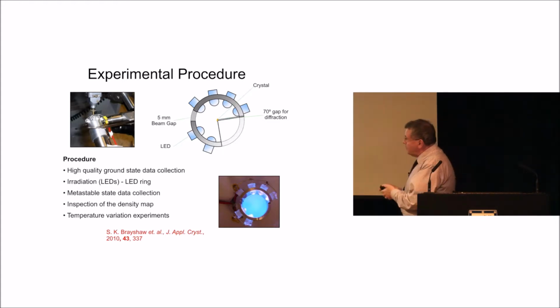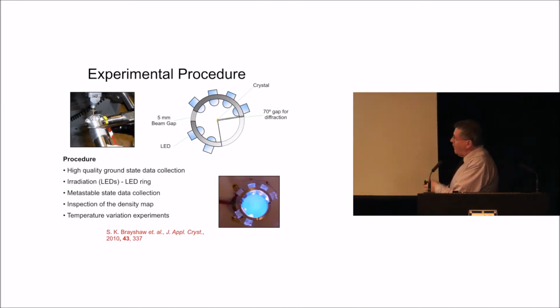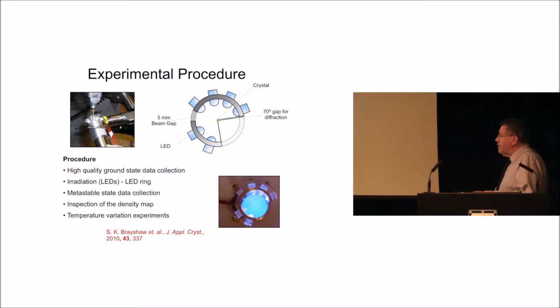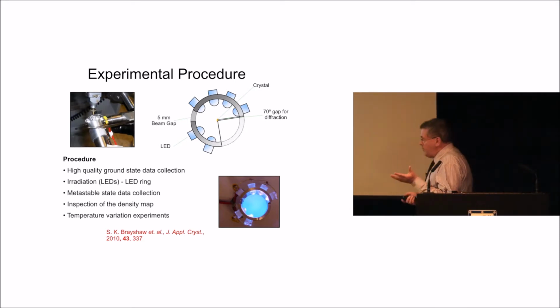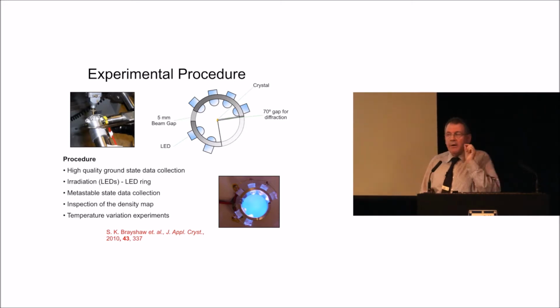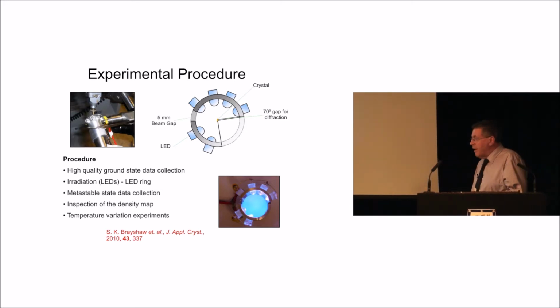You basically put your LEDs in a ring on the crystal cooling apparatus round the crystal, leaving in this ring space for the X-rays to come in and space on the other side to detect the diffraction pattern. And then what you need to do is a ground state data collection before any excitation, but at the temperature that you wish to carry out all the experiments.